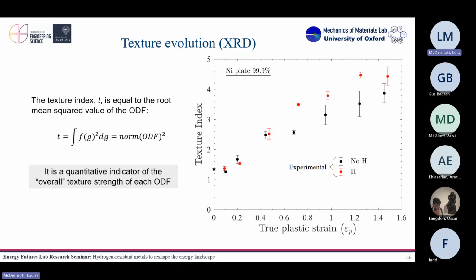If you look at the plot, the one published in Nature, we can see the evolution of the texture index versus the plastic strain. So it's how the material is texturized with different plastic strains. The non-hydrogen points are the blacks, and the hydrogen points are the reds. Those are a bunch of samples that were charged with hydrogen and cold rolled to those plastic strain levels. So what do you see there? What we can see is that the behavior of the samples with hydrogen and the hydrogen-free samples was pretty much the same up to plastic strains of around 0.5.